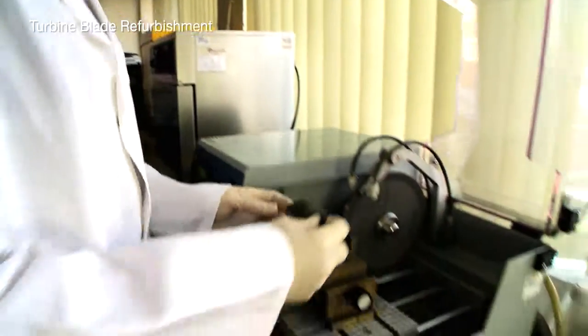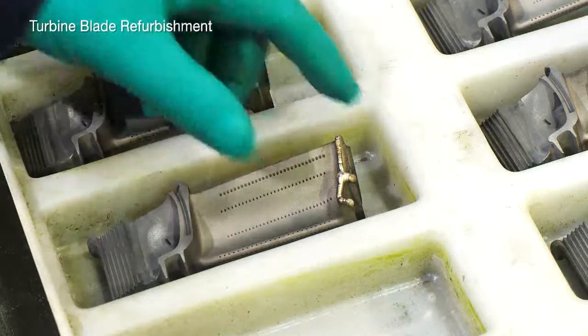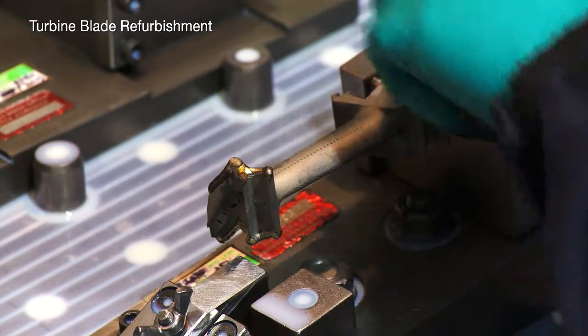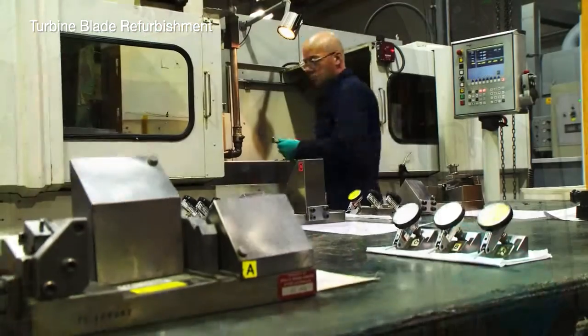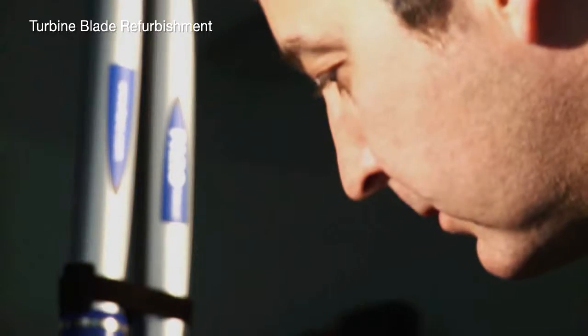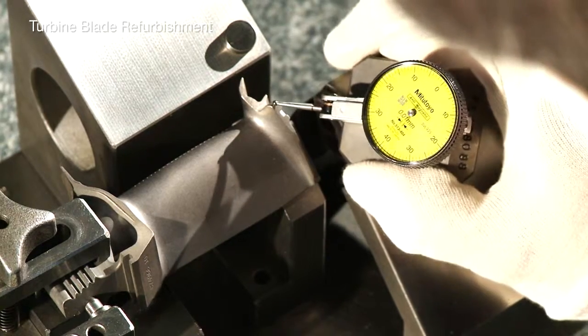Our recovery heat treatment process is supported on-site by our dedicated materials laboratory, which undertakes microstructural assessments and creep void analysis where appropriate. Final machining of turbine blades is carried out on the creep feed grinder to achieve finished dimensions of the interlock and seal fins. This is followed by the reapplication of platinum and aluminide proprietary protective coatings. The final overhaul stage for turbine blades involves measurement of all dimensions to ensure blades are within exacting specification.